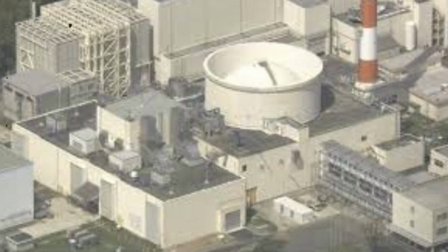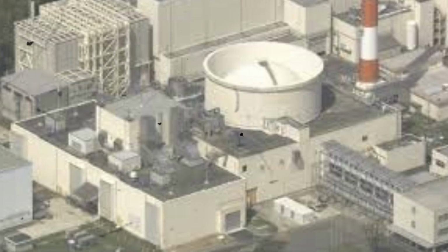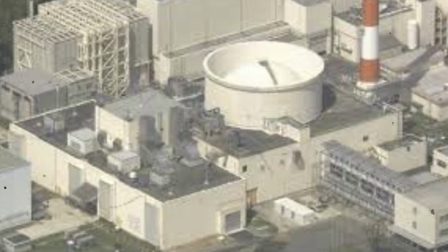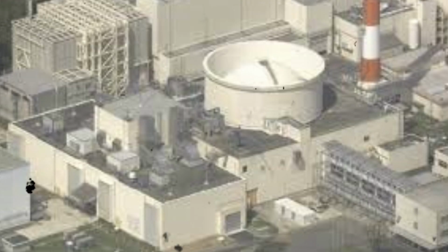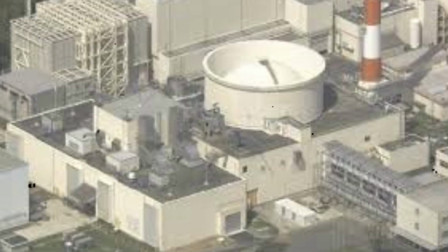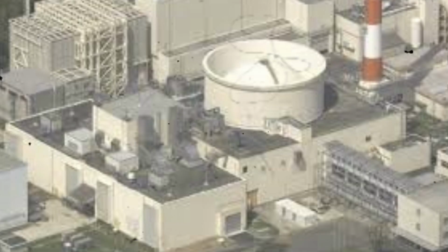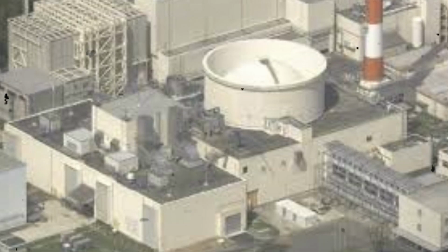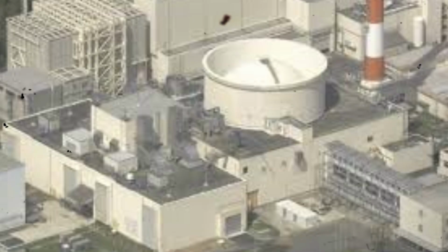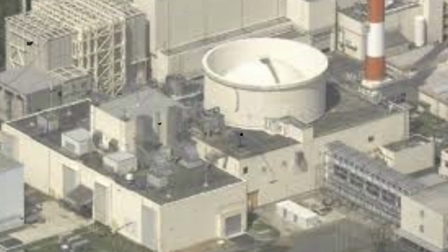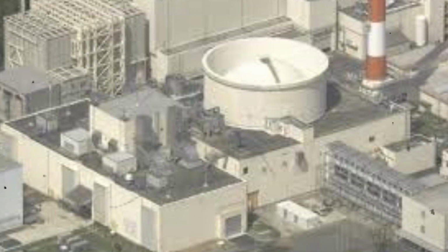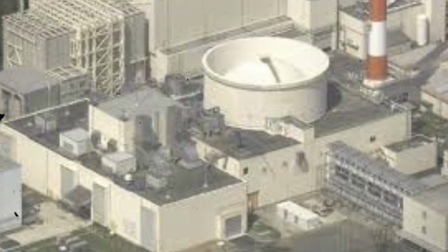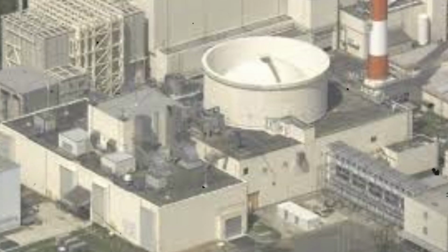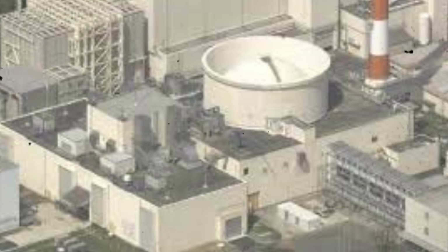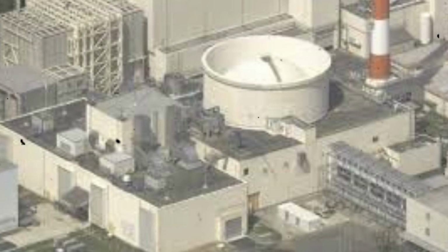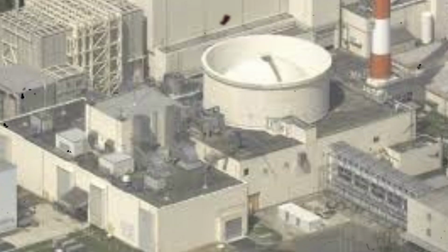specific failure mechanism. The fire detection responded to sodium combustion, but could not quantify the leak rate or predict leak progression. The leak detection confirmed sodium presence, but provided no information about the failure location or structural condition of the affected component. Microscopic examination would later reveal that the thermocouple well failure had been months in development. Fatigue crack initiation occurred during an early period of 100% flow operation, when vortex shedding around the sharp taper geometry created oscillating stress concentrations at the root of the tapered section.